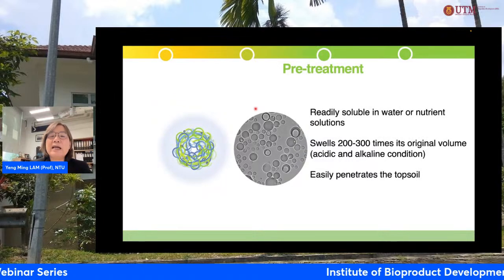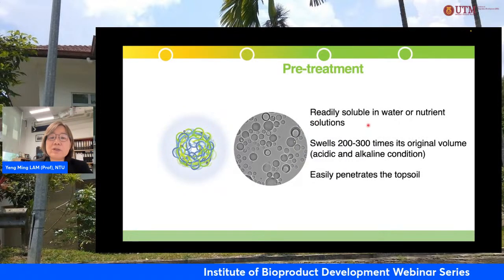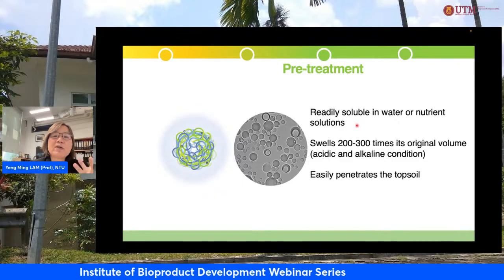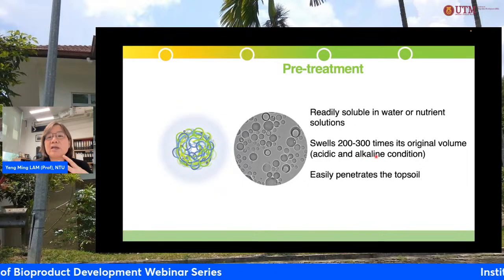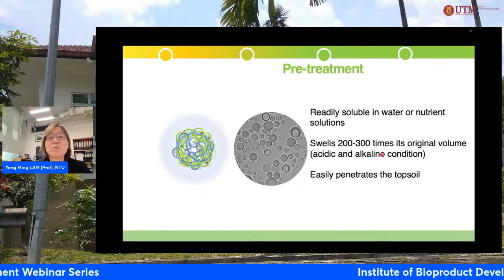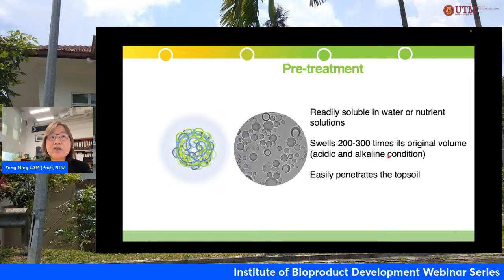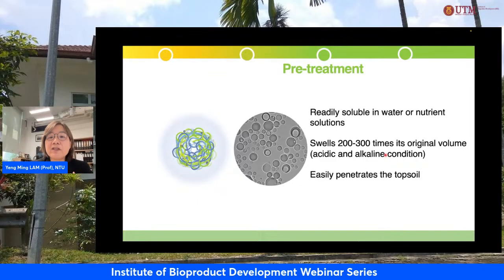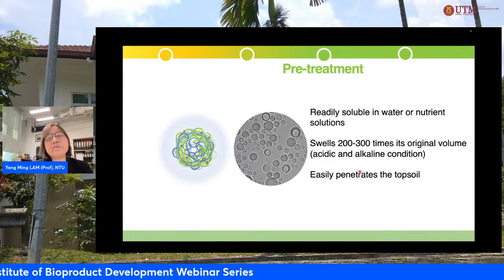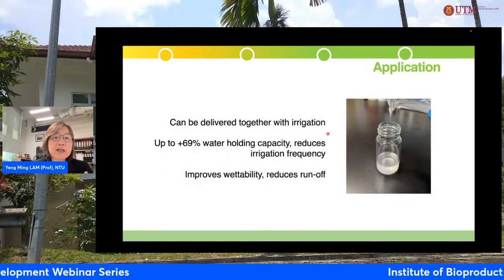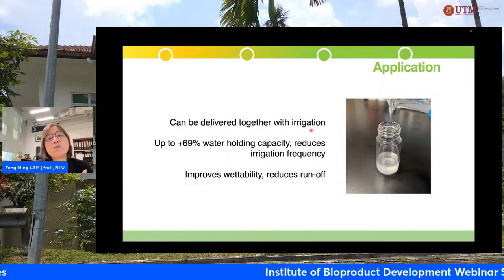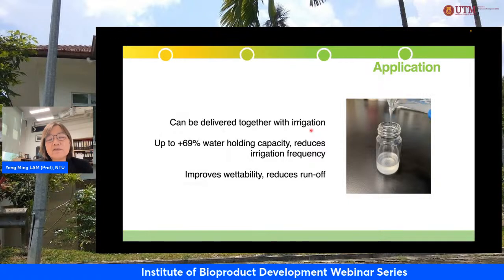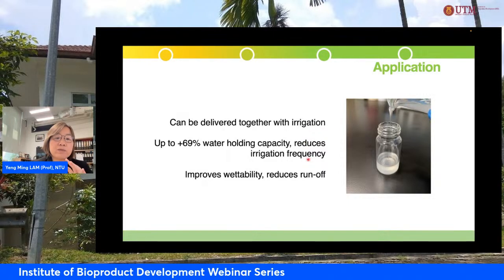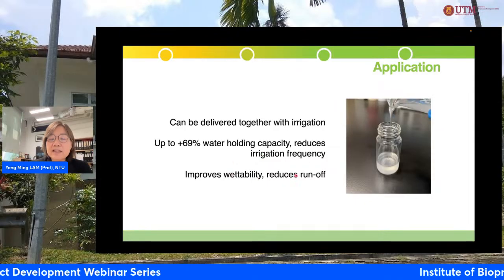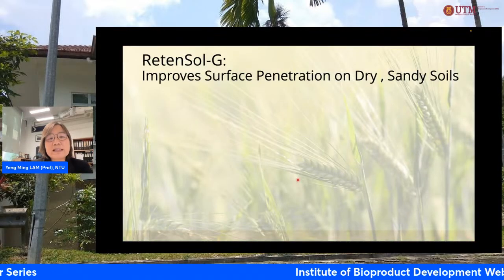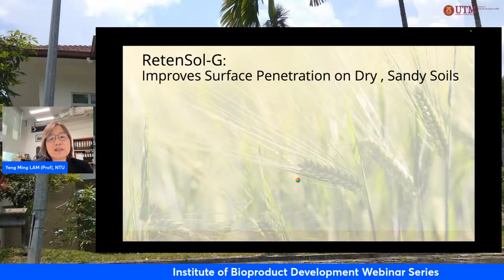So this powder will swell in the presence of water or nutrient solutions. It will swell to 200, 300, 400, 600 times its original volume. So it can take up water. And in any acidic or alkaline condition, the swelling behavior doesn't get affected. It can easily penetrate the topsoil, so it can be delivered together with irrigation, together with fertigation. It can hold more than 69% water capacity now. And it also improves the wettability and reduces the runoff. So this is an example of how the performance of this material works.